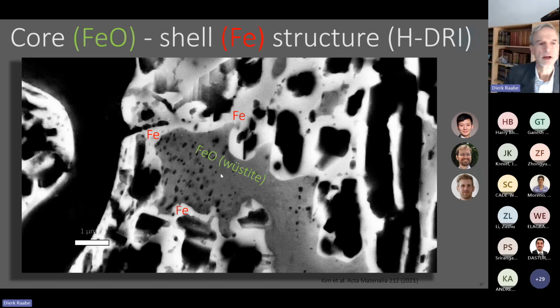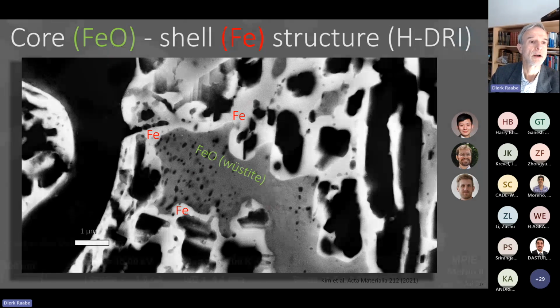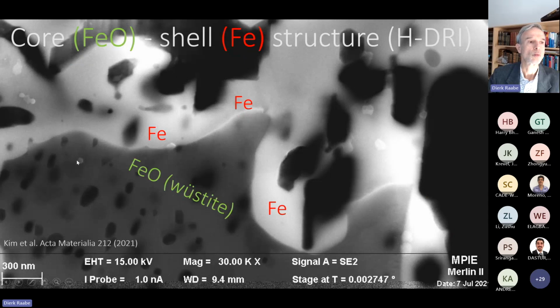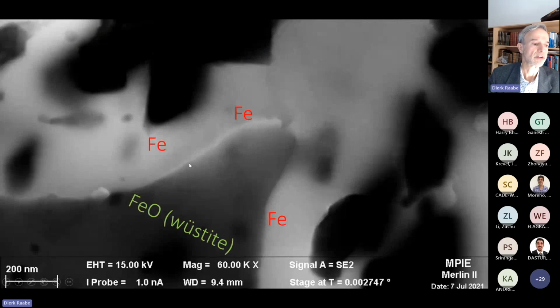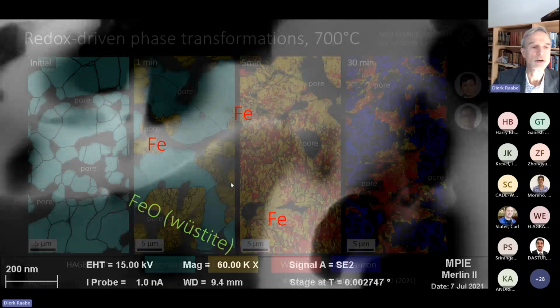The porosity comes from the fact that during the preceding reduction stages, you of course lose oxygen, and the oxygen loss happens primarily at the reaction interfaces, and these nano voids or nanopores are then undergoing coalescence into bigger pores. Much of that, I think, happens at the immediate reaction interface already, because their kinetic also of coarsening is highest. And you also see that when such a wüstite is towards the end of the reaction process in such a reactor, completely surrounded by relatively dense iron, here's an even higher resolution, then you can see that the kinetic bottleneck is to bring the oxygen outbound through these relatively dense iron layer to the next surface where it can react with the hydrogen to form water.